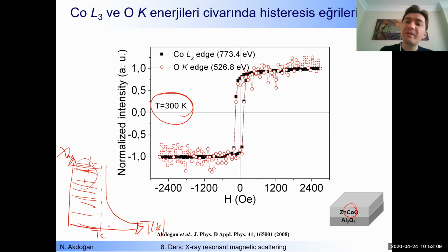At low temperature, the mechanism is the same. Measurement steps are also the same, okay? But you have to be careful with ice formation on the surface of the material at low temperatures. If the vacuum of the system is not good, then there will be ice formation on the surface of the thin film. Then you will have difficulties with the sample alignment, because there will be diffuse scattering due to the ice formation on the surface. So at low temperature you must be very careful about ice formation on the surface. Other things are the same as what you do at room temperature.